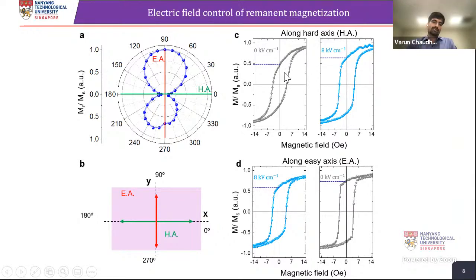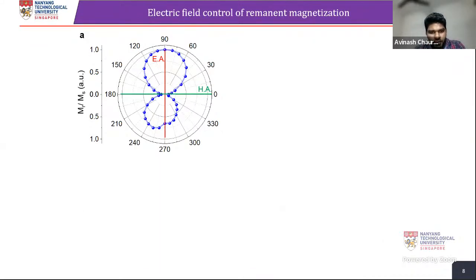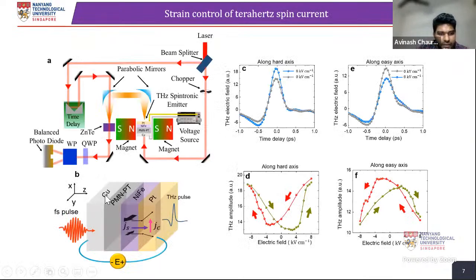But in VSM, when you have contacts, how do you apply the electric field there? For that, we had this device. Our main functional device is NiFe, Pt, and the PMN-PT, which is a ferroelectric, and we deposit copper at the bottom on a both-side polished substrate. The copper is not very thick because it should be a little transparent. Then we make electrodes from top and bottom and apply voltage using the 2410 source meter that we have. We can apply fairly high voltages. Okay, thank you.